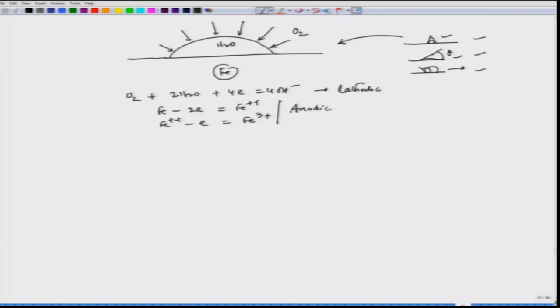Initially the partial pressure, or the oxygen concentration, throughout this water droplet is almost at a similar level. So in the beginning both those reactions will happen statistically uniformly over the surface. If I consider this section, in the beginning we have all three reactions, and these are actually forming Fe(OH)2 as well as Fe(OH)3.